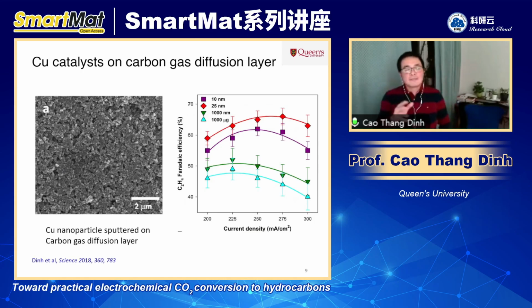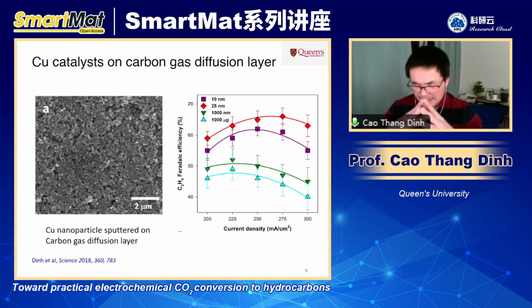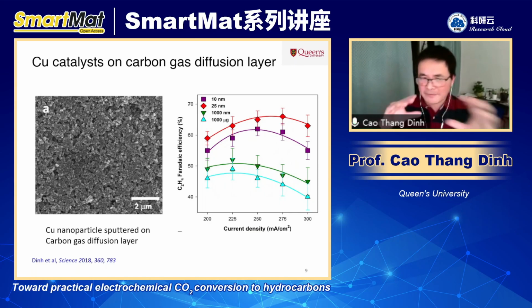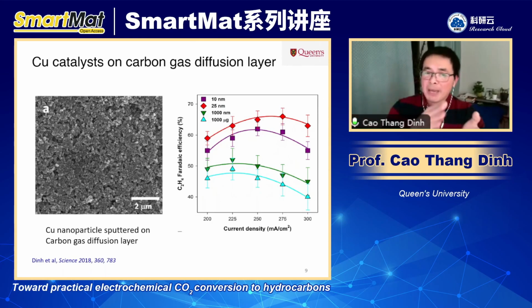So about 6 or 7 years ago, when we started working on this technology, we used exactly the same gas diffusion layer that people use for fuel cell technology, right? So a carbon-based gas diffusion layer, and then we sputter a thin layer of the catalyst on top. We use physical deposition to grow a thin layer of metal, in this case copper, on the surface of the carbon gas diffusion layer. It looks something like this on the left here. And it worked perfectly when we ran the CO2 conversion in an alkaline electrolyte. We got pretty high selectivity for ethylene in this case.